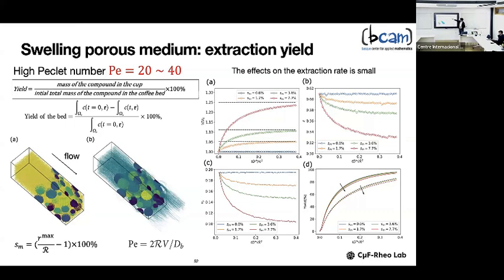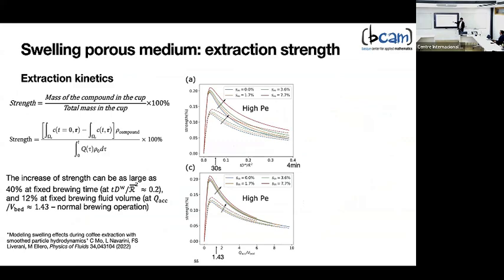But the effects for two different Péclet numbers, 20 and 40, on the extraction kinetics are not very much. You can see that the different degrees of swelling, for example, if you focus on the continuous line, is just a minor change in the yield extraction. What really changes with swelling is the strength. You can imagine the strength is much more sensitive to change in the concentration. This is an estimate of the concentration. And here you can see that, if you look at the strength in terms of the brewing time, there is a difference between the blue and the red line. Therefore, there is an increase of the strength in the coffee beverage as an effect of an increased swelling of the particle.